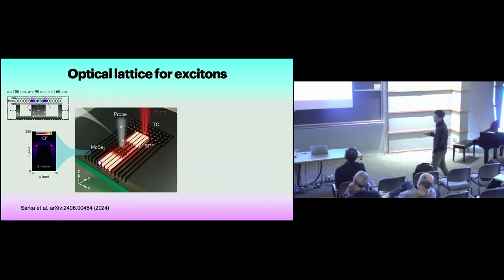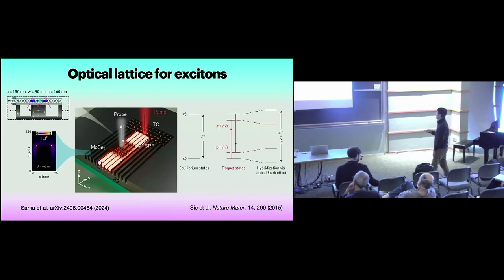And how does this affect the excitons? Right, so actually we use this now quite well-established idea of using the AC Stark shift. If you drive the system just below the exciton transition, you induce an AC Stark shift that blue shifts your exciton, and it's proportional to the intensity of your laser. So here, if I look at the cross-section, the intensity is maximum at the edge at these two bunny ears, and it's minimum in the gap and in the middle. So this creates an AC Stark shift where you have high energy right over here, but low energy over these three spots. So, okay. I'll wrap up soon.